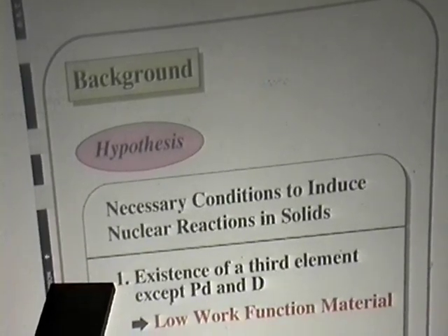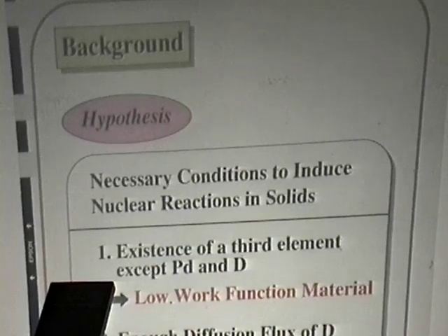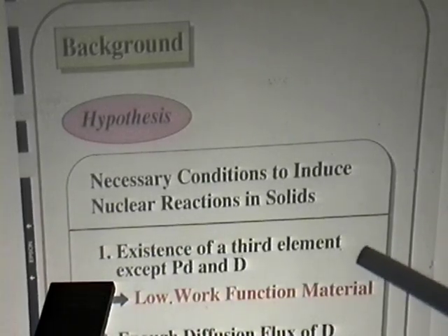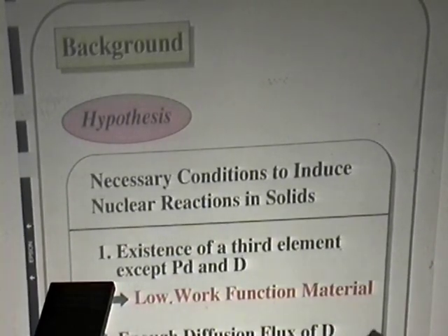This is a hypothesis of our study. We examined palladium cathodes by EPMA or XPS, and we conjectured that certain impurities play an essential role in causing nuclear reaction. So we assume that the necessary conditions to induce nuclear reaction in solids are: 1, existence of a third element except palladium and deuterium; 2, enough diffusion flux of deuterium; and 3, high D/Pd. At present, we suppose low work function material is a candidate for the third element.